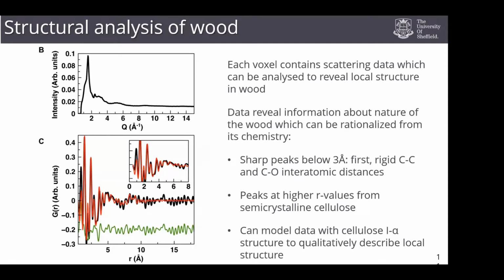very often we use X-ray diffraction. X-rays come in, they diffract off our materials, and we can tell the structure of that material. That's really nice if you've got a beautiful crystalline material that repeats nicely over infinity. If you've got teeny tiny bits and pieces within a degraded piece of wood, you're not going to have that beautiful extended crystal pattern. You might just have very short range where order exists. And that's happened here. You've got this short range where order exists. That's what these sharp peaks are telling us. And then that order just sort of drops off because everything at higher distances, this is angstroms, there is no order at those higher distances.